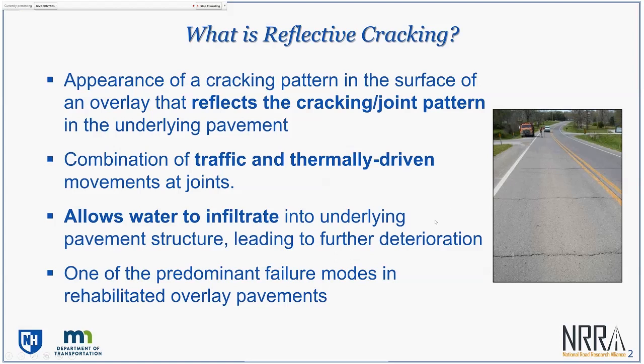Usually the cause for these is a combination of both traffic and thermally driven movements that occur at underlying joints and cracks, and these movements cause very high levels of stress concentration in your asphalt overlays, leading to their fracture. The challenge with reflective cracks is that because of this excessive movement at this location, these cracks have a tendency to deteriorate at a very high rate.